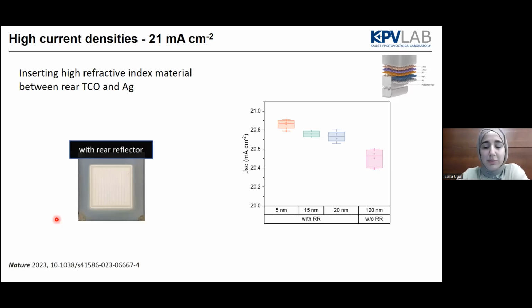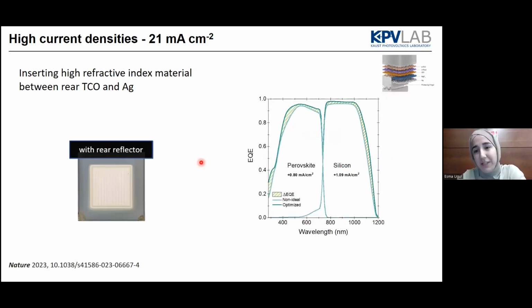using some models that I'm not really an expert of. But what we have at the end, with the help of the blue response on the perovskite side, and also the enhanced IR response from the silicon side, is that we can get nearly 1 milliamp per centimeter square enhancement compared to our previous, let's say, optically non-ideal devices. This is the optimized one we are working on now.